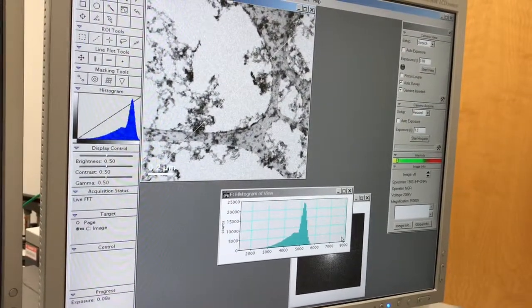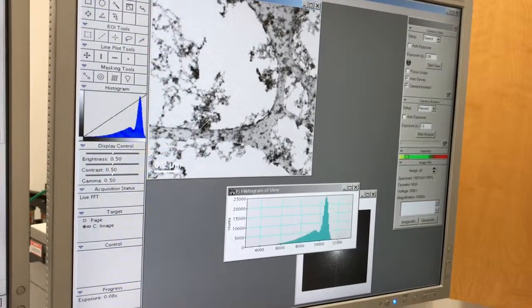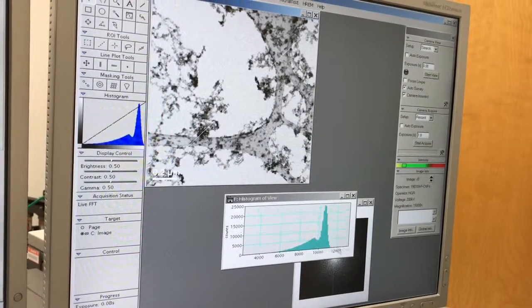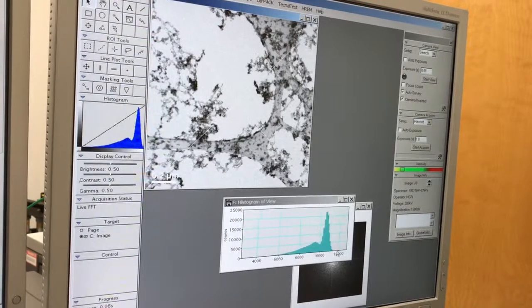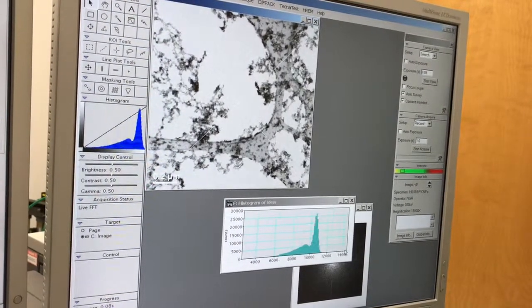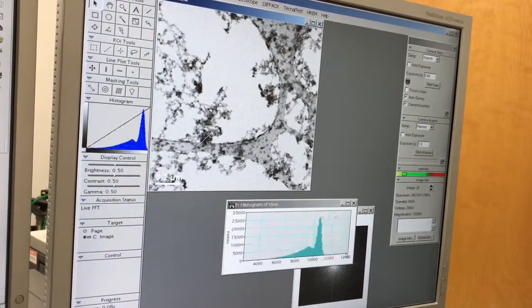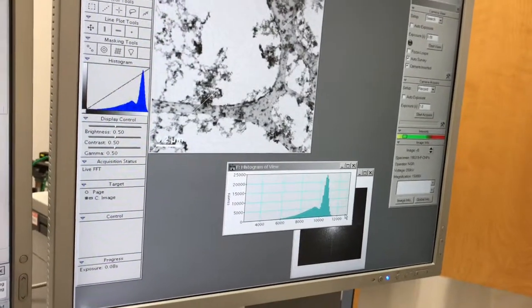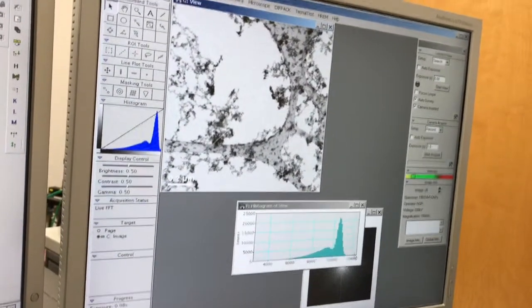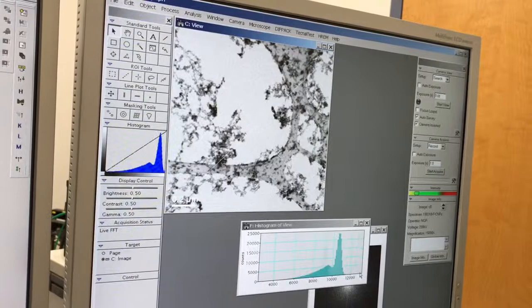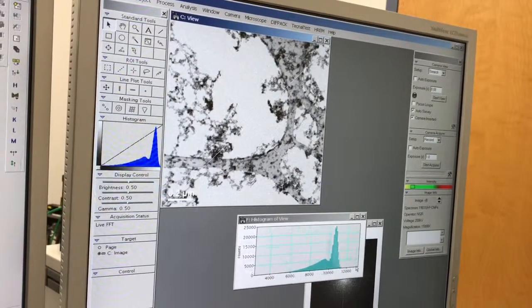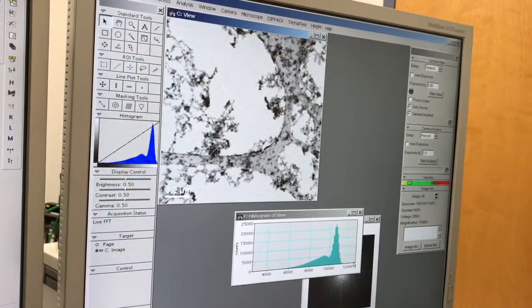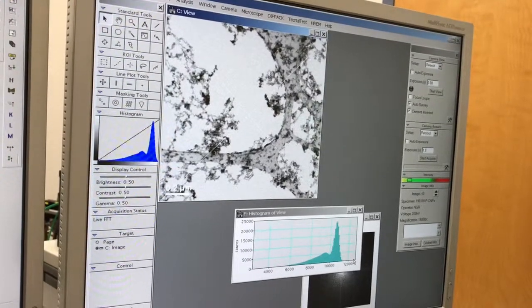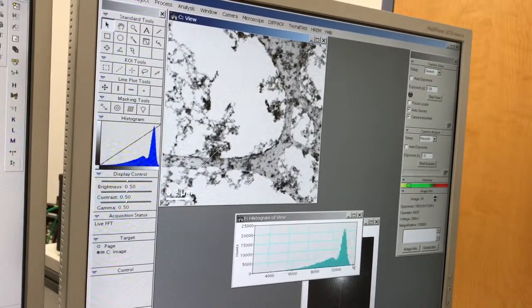I go up again, and now you can see it's approximately doubled. The max counts went from 6,000-7,000-ish to 12,000-ish, 14,000-ish. So that's another key thing to remember with most digital cameras: they have a linear response. So your max signal scales linearly with the exposure time.